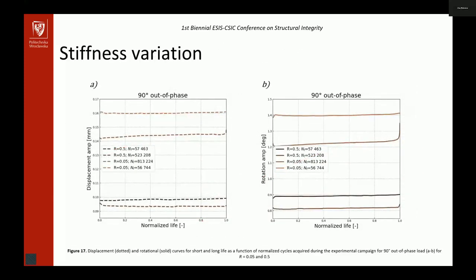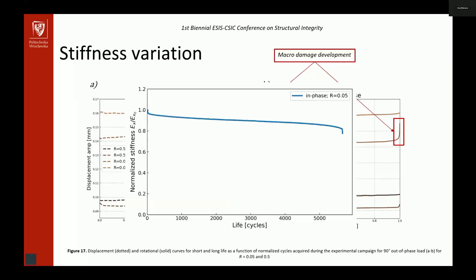And now stiffness variation. This stiffness variation has been presented for the displacement amplitude, and we see the gradual change in displacement. The fatigue test was force controlled, and in the last stage we see some progressive change in displacement, which we associated with the macroscopic damage development. It can also be seen here. This is from the biaxial extensometer, and we see a gradual and linear decrease in normalized stiffness.